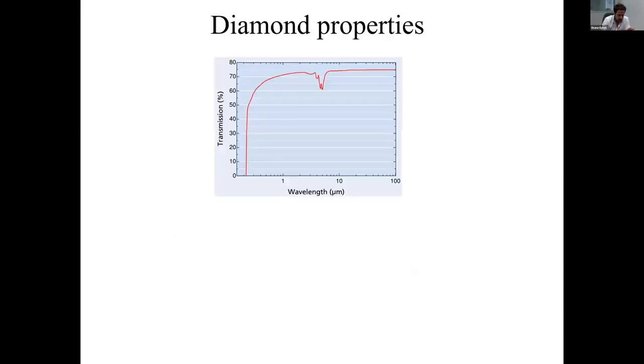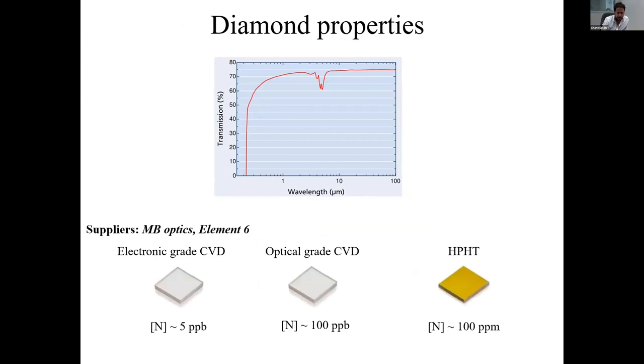To give a quick idea of the diamonds we're working with, again, we're using synthetically made diamond. Here shows the lovely transmission window of diamond, which is great even up to the terahertz. We're typically buying from either MB optics or Element Six, two of the main CVD diamond producers. Depending on the purity, you can go from low grade, made with a different process, high pressure, high temperature, on the right, the yellowish diamond, where you have a nitrogen impurity concentration of around 100 parts per million. Working your way up to higher purity and more costly samples, optical grade, which is typically what I use for my research, we have nitrogen concentrations of around 100 parts per billion.